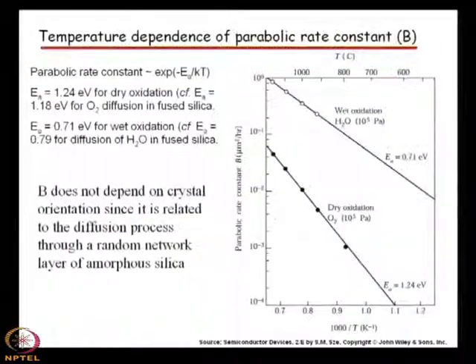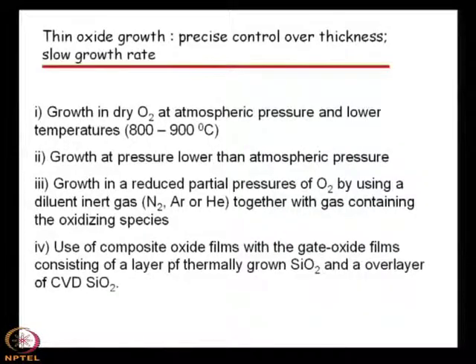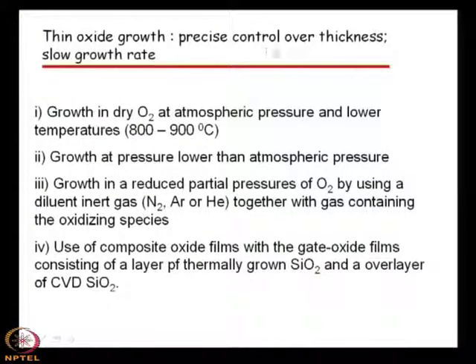This is thermal oxidation, because we shall come across other oxidations also, like the CVD of silicon, or other types of oxidation, where we shall find that there are other applications also, not only making the gate oxide: in some cases for isolation, in some cases for making the mask for the diffusion or lithographic pattern. There thick oxide layers are grown, and in that case obviously we will not use dry oxidation, rather we shall go for wet oxidation or oxidation by the CVD technique or other techniques that we shall discuss in later stages. So, precise control is important, and the growth rate must be slow enough.